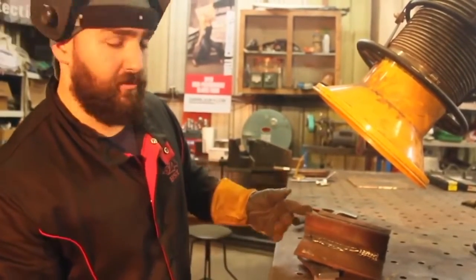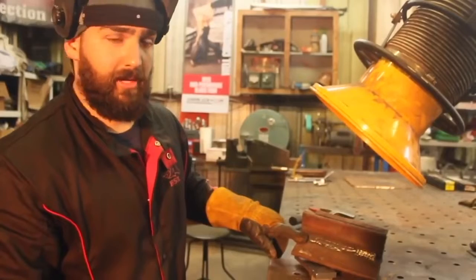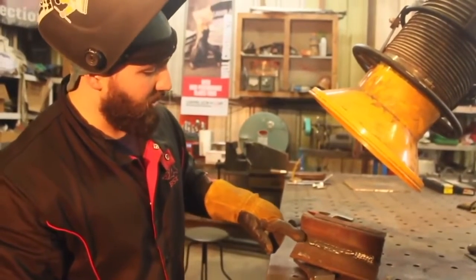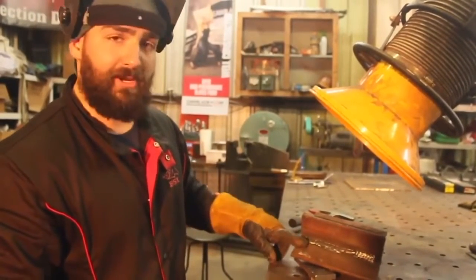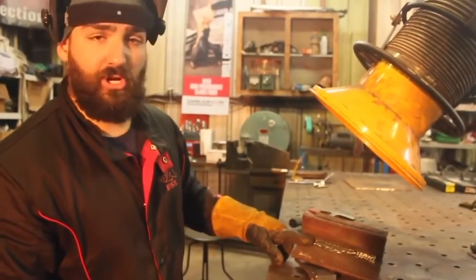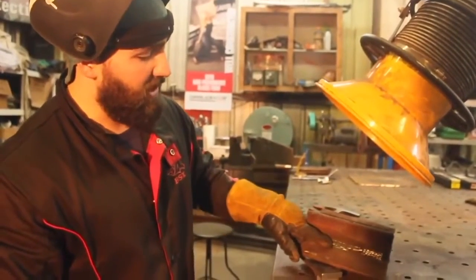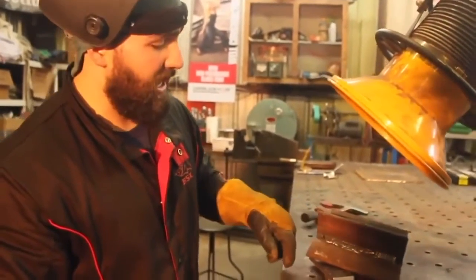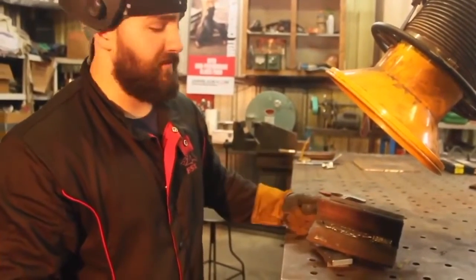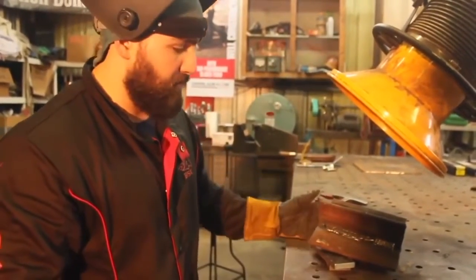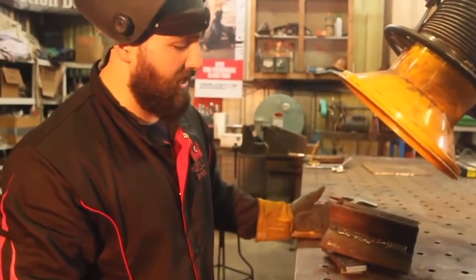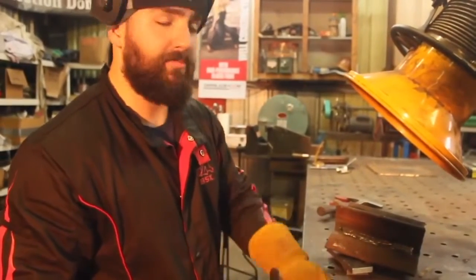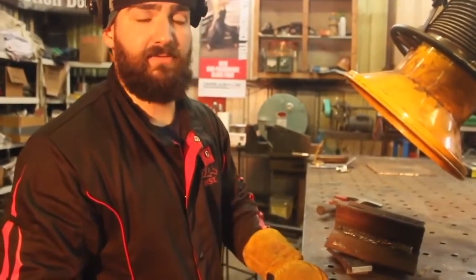So just to recap, we have low voltage here and correct wire feed speed, where the low voltage allows our weld to not penetrate into the base metal, which causes lack of fusion. And then we have correct voltage and a low wire feed speed, which makes for a much longer weld, takes more time, and it can damage your tip and also the other components that are inside the nozzle and the diffuser.